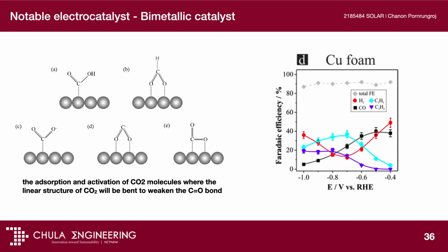I would like to point out that one of the most notable catalysts or co-catalysts to put on your system is copper. Copper has a very interesting property. It forms bonding with CO2, right? It activates your CO2, but it forms a very weak bond with the CO. So normally it takes your CO2, reduces it, gives the electron to CO2, and CO2 becomes CO. And then what copper does is couple that CO that sticks onto the surface, and they combine it and create a longer bond. So that's the copper property.